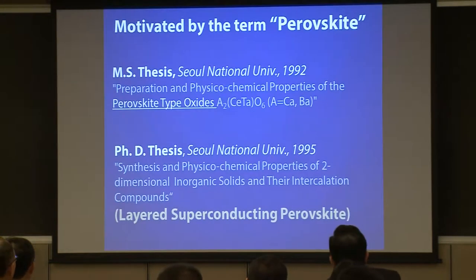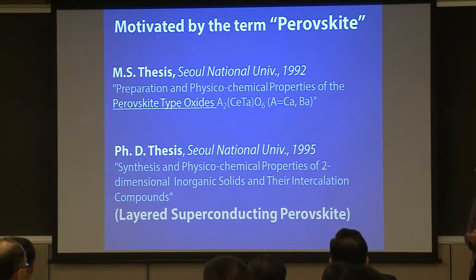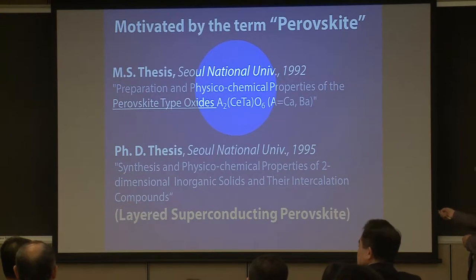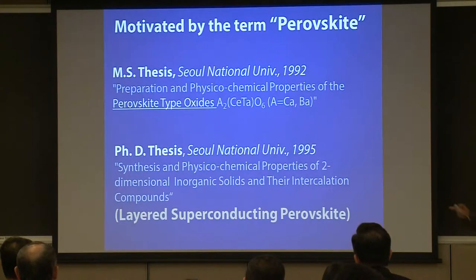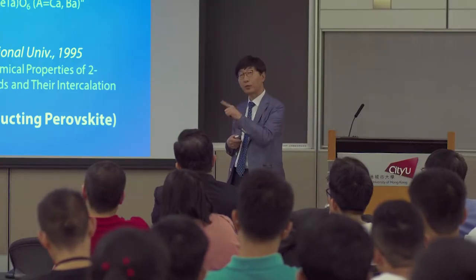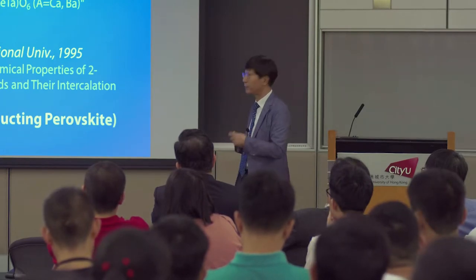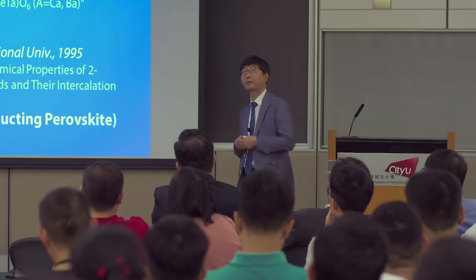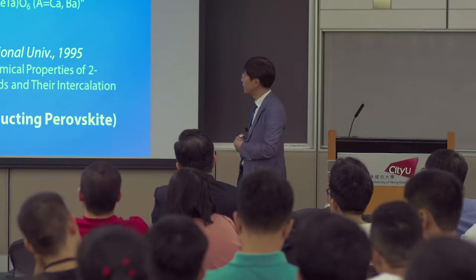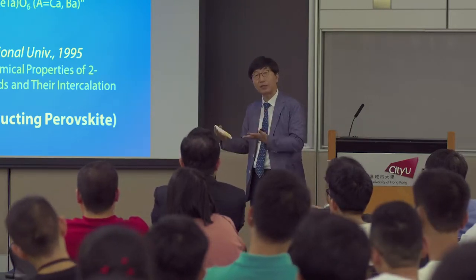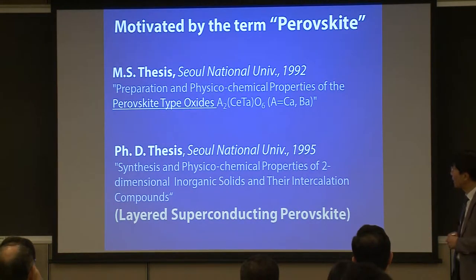his work. But I was very motivated because my background in my MS and PhD work was based on perovskite oxide. So I know a little bit about the perovskite structure and property. For instance, during my MS thesis, I studied the double perovskite structure, the calcium or barium cerium tantalum oxide material. In this case, the cerium and tantalum may have 4+, 4+, or 3+, 5+. Depending on the oxidation state, we have different chemistry, d1 chemistry, f1 chemistry, which can affect the magnetic property of this material. So it was interesting, but I was not actually interested at that time because I would like to work on superconducting material. So in my PhD course I studied layered superconducting perovskite materials.